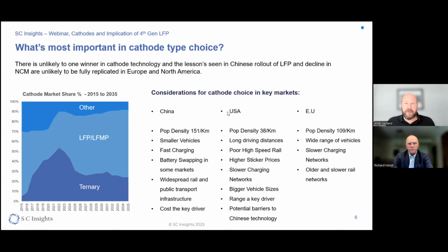So when it comes to cathode choice, obviously the two main groups are ternary cathodes, typically NCM or NCA mixes, and then you've got your LFP type cathodes. We group those together here, and you can see our view as to how that's likely to develop. Now, what you had over the past 10 years was this big run up in NCM type cathodes, particularly high nickel, and single crystal mid nickel cathodes, increasing the amount of nickel and reducing the amount of cobalt as thermal stability management got better.